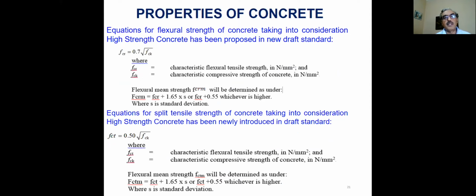Axial strength equation is same, but we have called it a characteristic value, and then mean value can be determined like this - as we determine for the compressive strength, it has to be characteristic plus 1.65 into standard deviation, or FCR plus 0.55, whichever is higher.